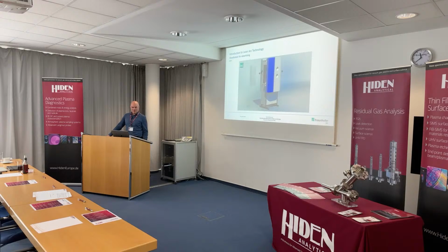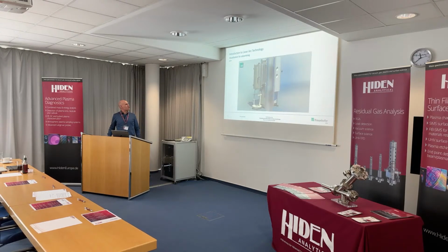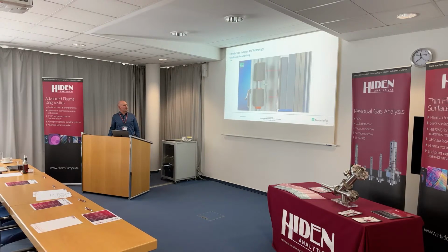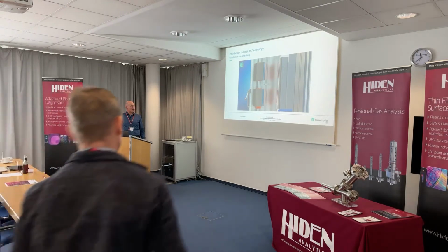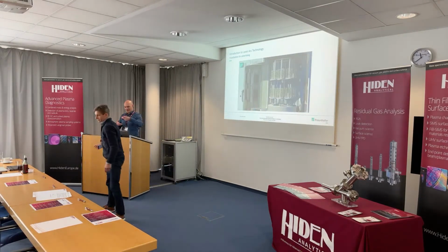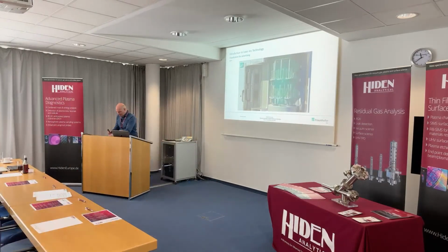Okay, this is some presentation, some video of our process, of our principle. This was the laser arc module attached to the cathode, to the chamber. Then you here now see the scanning laser and the arc spots on the cathode surface. This process is very fast. It's 150 hertz each cathode, and so altogether you get some linear carbon source. So now we can also go to the stream. And here you see now the plasma, and of course, PVD or laser arc as a PVD technique is line of sight. That means we always have to rotate our samples to make them coated all around.